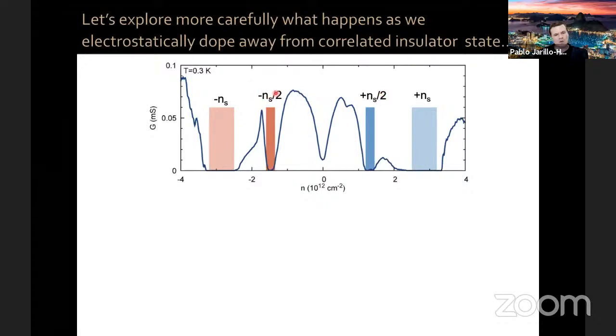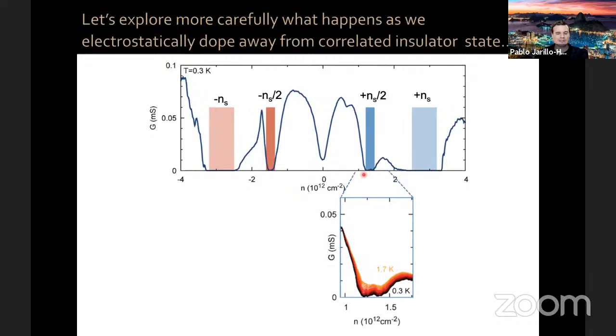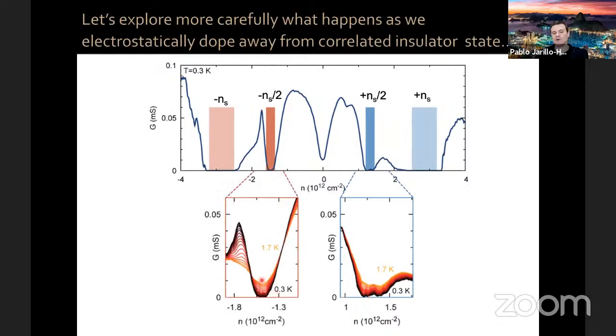We were doing temperature dependence around these correlated insulator states. Around the correlated insulators for electrons, we realized that as you cool down, the conductance decreases. That's the expected behavior of an insulator: you cool down, less conductivity. However, for the correlated insulator state for holes, right at the insulator, the same was true. If you cool down from 1.7 Kelvin to 0.3 Kelvin, the conductance decreases. But right next to it, as we were adding a few holes to the system, you can see that the conductivity was increasing as we were decreasing temperature. So that conductance enhancement was very suspicious.